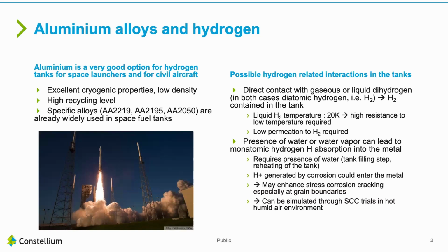We may imagine that during the filling step or the reheating of the tank, there could be some water or water vapor that can lead to the presence of monoatomic hydrogen that could then be absorbed at the surface. Hydrogen can be generated by corrosion and then enter the metal. This effect can be simulated through stress corrosion crack trials in hot, humid air or in a chloride environment.